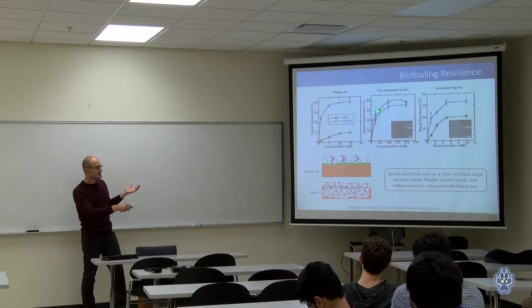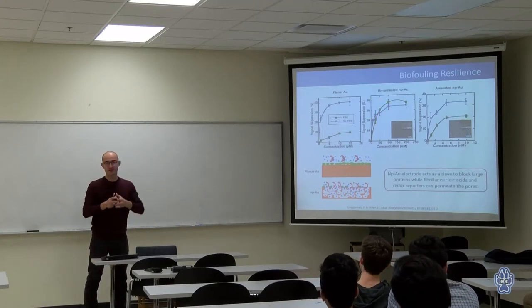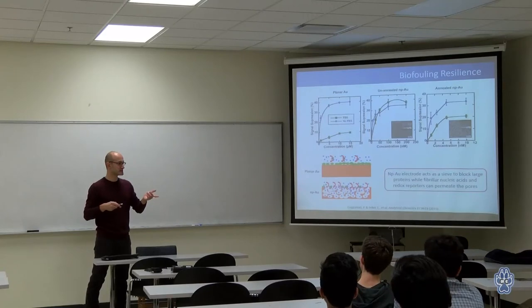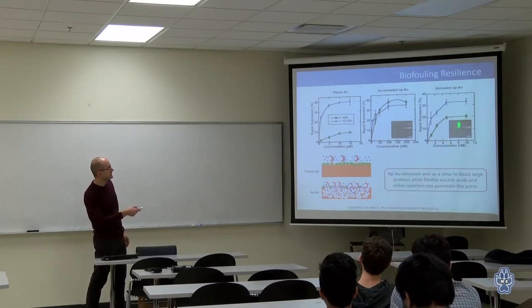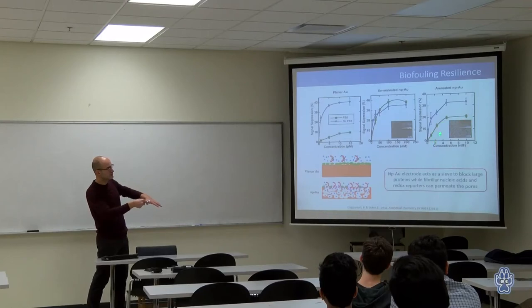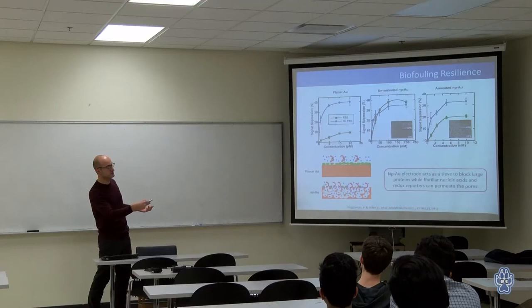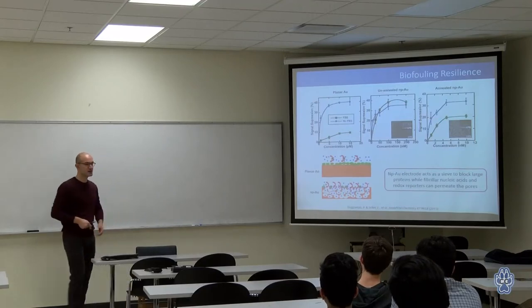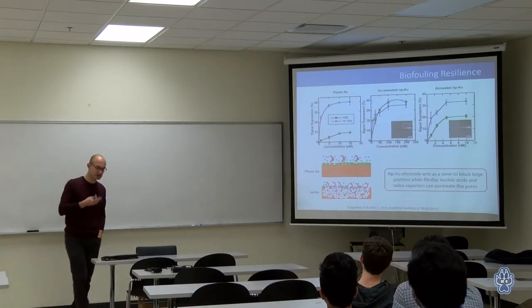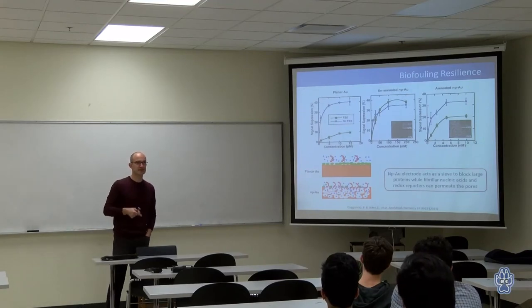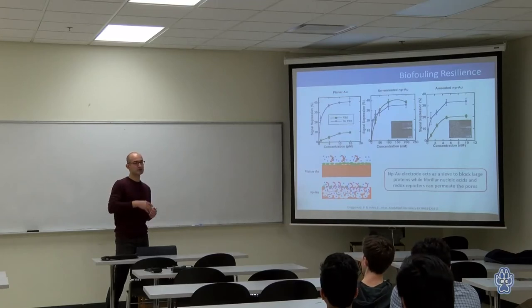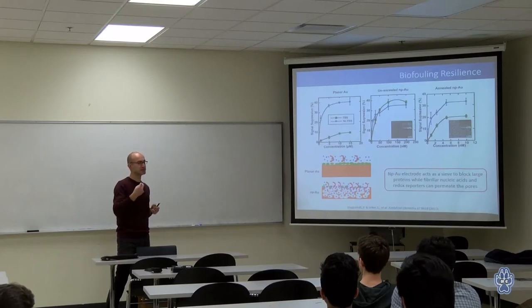To test whether this is the case, what we could do is enlarge the pores through that annealing process. And just as we see here, now proteins can go deeper into the pores and inhabit deeper pores, and it does not work as well anymore. So it begins to approach that planar gold case. This is actually very important, because if you're trying to detect something in the field, like let's say you're in the field trying to detect some pathogens, you would need to do all these purification steps to get the pure DNA out before you can apply it to the sensor.